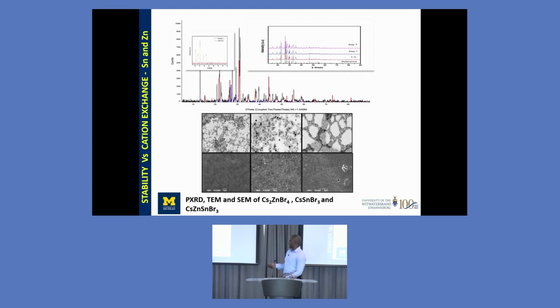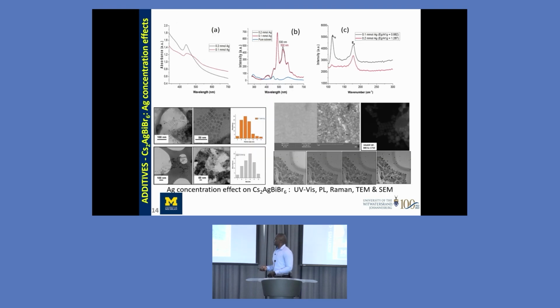So we had to get a synergistic effect between the two nanocrystals by playing on the concentration of zinc and tin and mixing them together. So when we play on the concentration after optimization, we could really get cesium zinc tin bromide with properties that are between the two compounds, and also the nature of the compound that we get. It was really stable, and the stability could be seen after days of keeping the sample under normal conditions.